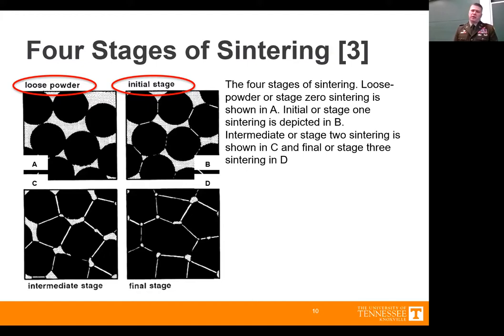My work specifically focused on loose powder in the initial stage. So rather than doing something to the loose powder, either pressing it or extruding it to try and increase the initial density before sintering, I kept it at very low densities. Most of my samples started out at somewhere between 10 and 20% theoretical density, and during the sintering process densified up to approximately 30 to 40% total theoretical density. So I never even got out of that initial stage sintering.